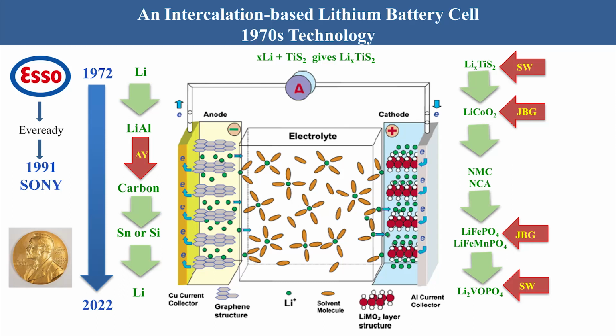So from lithium, we moved to other electrodes. Exxon had recognized the issue with lithium, so our cells that we made in the end used a lithium aluminum alloy. All of you in the semiconductor business fully know the last thing you want near any of your semiconductors is lithium metal. It reacts with everything. So it reacts spontaneously with aluminum to form a 1-to-1 alloy, and that's what we use in our cells. It doesn't work all that well. It works for maybe 10 to 20 cycles, but that's all we needed in those days, because the watches in our initial products were LED displays, not LCD. So you had to recharge the battery every 3 or 4 months, and that's where we used them.